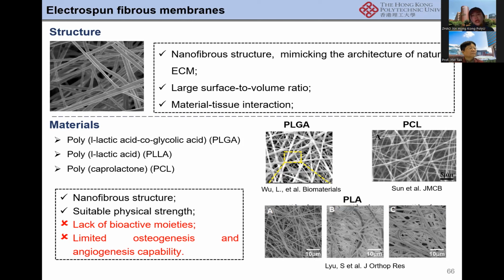It's just that the way we electrospin keeps changing, and there are many other ways to modify the materials and the structure, and give different properties to the fibers. The way I'm using them is that I make the materials themselves elastic. So we can make the electrospun fibers elastic. But there are also other ways, just by changing the pore shape, or immersing them in ethanol. They can change the shape of the fiber, or the shape of the pores, and then change the mechanical properties of the wound dressing.